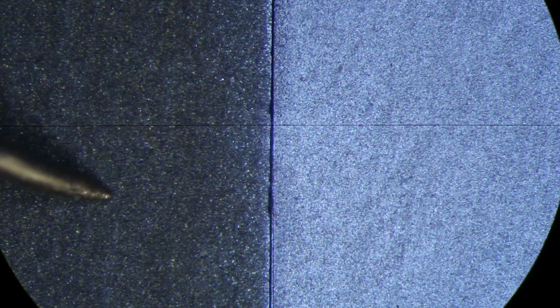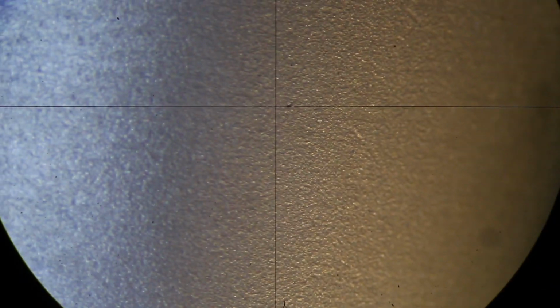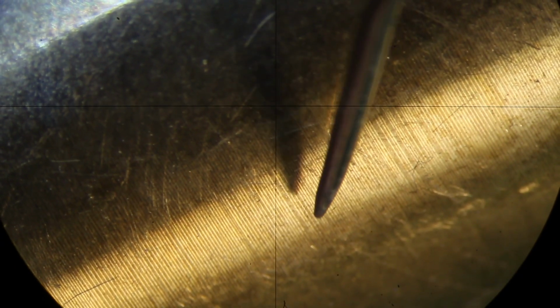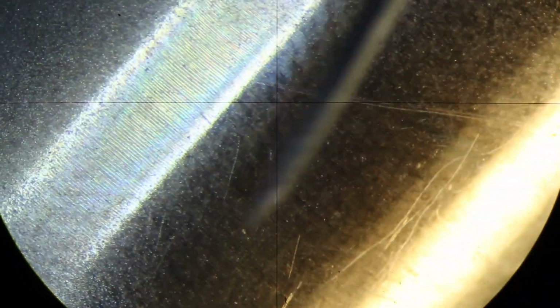Okay, this is a microscope view of the high-speed steel sine bar that I blasted. On the right side, this is blasted obviously, and this one over here still has the original wire EDM surface. I think this is a better example. This is the brass bushing that I blasted, or bronze. Here you can still see the lines from turning the bushing. These are spaced by the feed per revolution of the tool that was used when this part was made on a lathe. And when we go up here where I blasted the part, these lines are gone. A very homogeneous surface here, a little bit rougher than the turned finish.